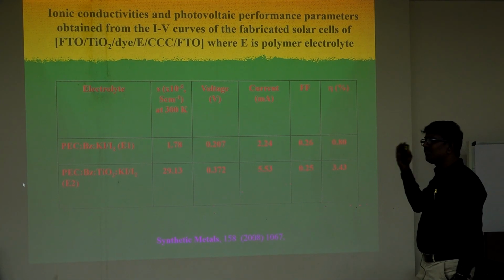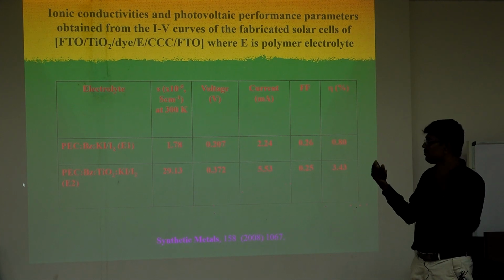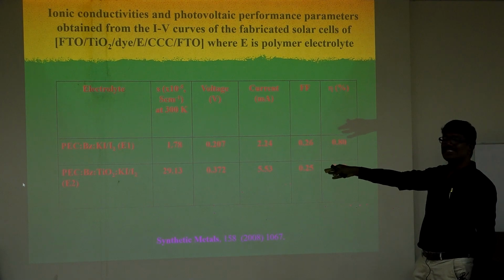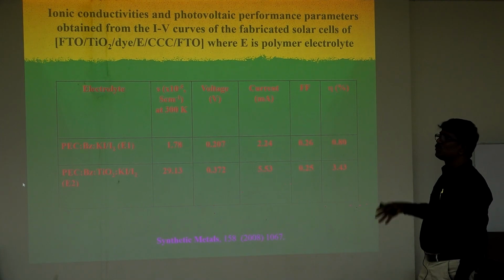Okay. So then people may ask, why use only your benzidine? We can use other materials also. So we are teaching classes now. When you teach classes, we can think which compound is better. Then we prepared heteropolytungstic acid. This is one of the inorganic materials. At the MSc level, you can teach heteropolytungstic acid. So that material we mix instead of your benzidine. Heteropolytungstic acid is a colorless compound. When you apply light energy, it forms a new compound called heteropoly blue, which also absorbs light energy around 760 nanometers. So we use this compound to make a new solar cell, and we got good publications also comparatively to this one. That's also what we did actually.